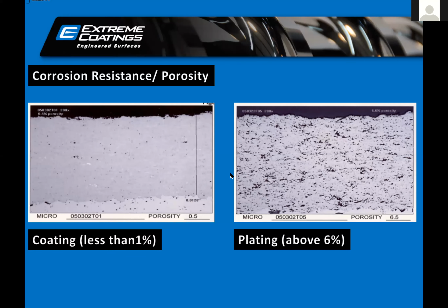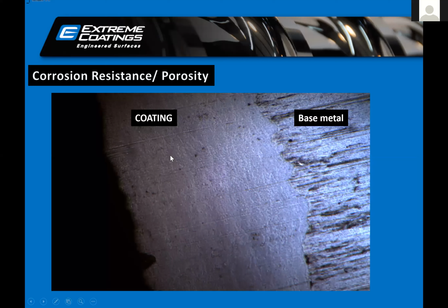So there is no chance of acid entering the base metal. This is the cross section of our coating, and this is the base metal. You can see there is hardly any porosity in the coating.